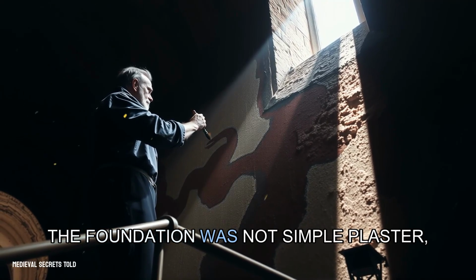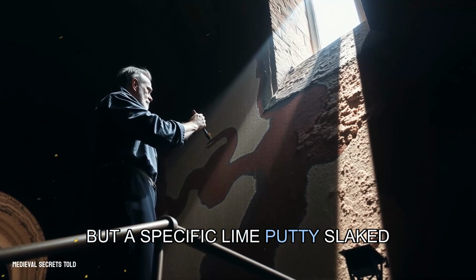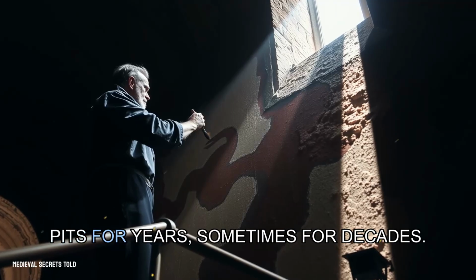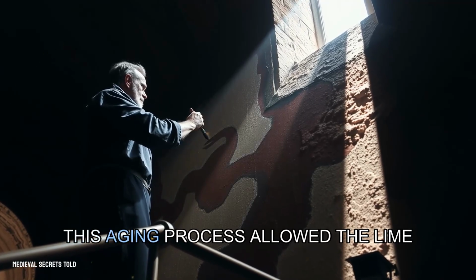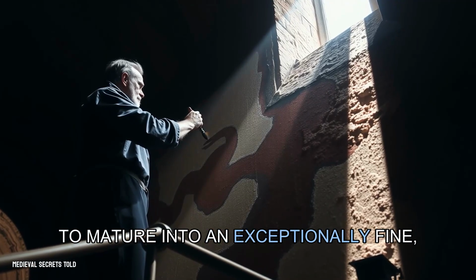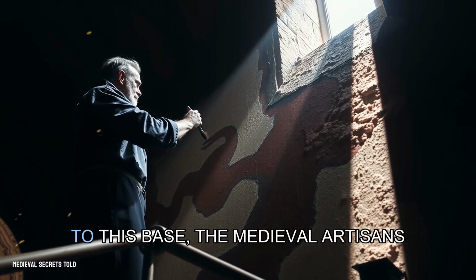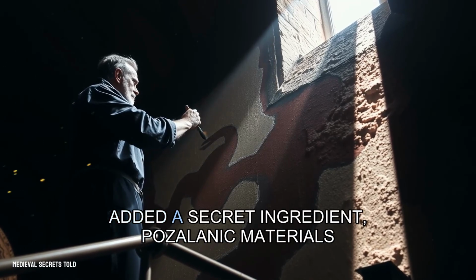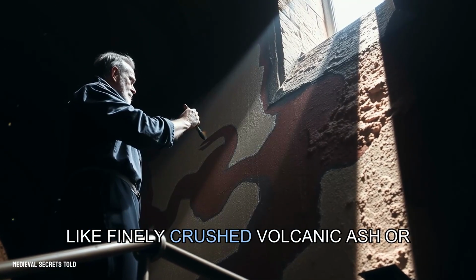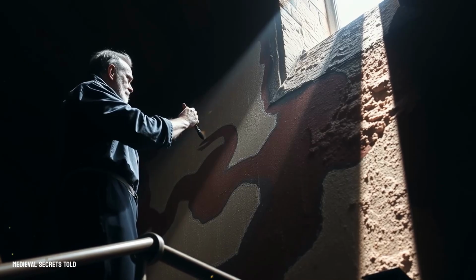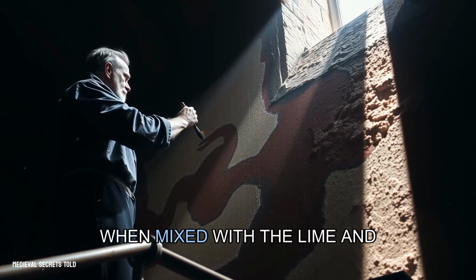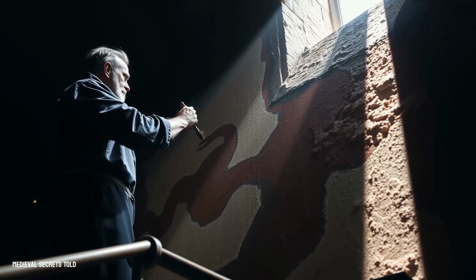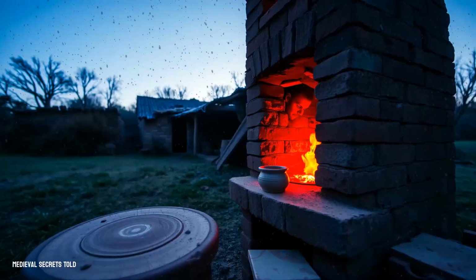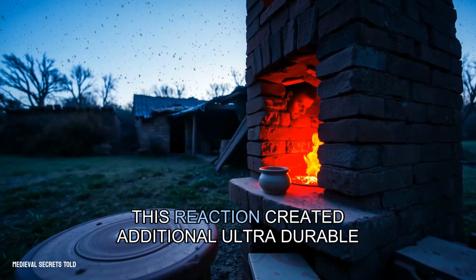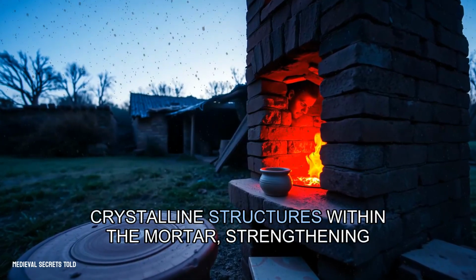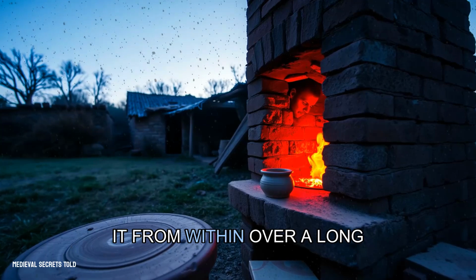eternal. The foundation was not simple plaster, but a specific lime putty, slaked with water and then aged in pits for years, sometimes for decades. This aging process allowed the lime to mature into an exceptionally fine, smooth, and reactive paste. To this base, the medieval artisans added a secret ingredient, pozzolanic materials like finely crushed volcanic ash or even powdered brick. These additives were the genius stroke. When mixed with the lime and applied to the wall, they triggered a secondary, slow-burning chemical reaction known as a pozzolanic set. This reaction created additional, ultra-durable crystalline structures within the mortar, strengthening it from within over a long period.